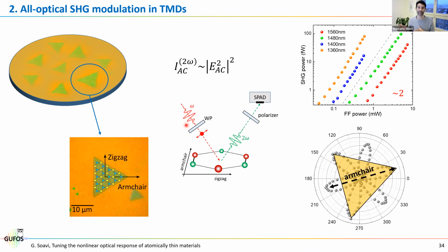In TMDs, instead, all the fundamental wavelengths are well below the gap for us. If you look here, for instance 1560, even two photons is below gap, right? It's below, because the MoS2 gap is at 680. So the only one that is resonant is this 1360. But even in this case, the absorption is very low, because it would be a two-photon absorption on the 1s state that is forbidden by optical selection rules. So this is really a parametric process, if you want. There is no energy transfer to the material.